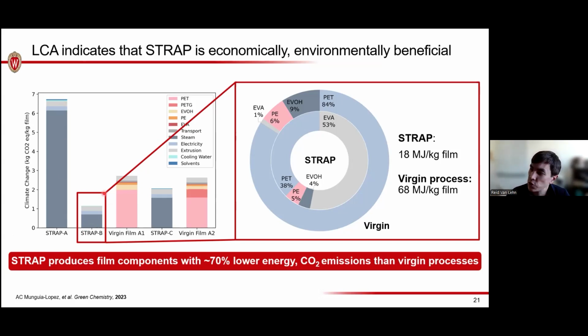So that's when we started to do STRAP B. This is where we chose a new set of solvents where we induced precipitation solely by reducing the temperature. So now we have a single solvent, and it's essentially a temperature swing process. We heat up to dissolve, we cool down to precipitate. And that's what STRAP B is. STRAP C is actually, we just do a different film. So this was just a comparison of if we had different films with different compositions, what is the sensitivity to film composition, and we see that it's still less than virgin film production.